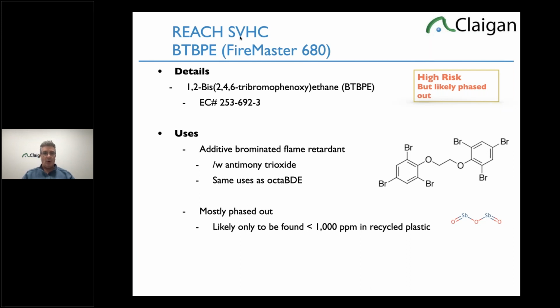Firemaster 680. So this is another brominated flame retardant. It's been phased out years ago to the point where most labs, including ourselves a couple months ago, didn't have a test for it. Even we're testing brominated flame retardants. Nobody tested this one. This phased out a long time ago. Where we could see it is recycled plastic, but generally around 100 ppm. This one's pretty low risk. It's also a pretty poor brominated flame retardant. It only has 6 bromines. That's actually not very good.